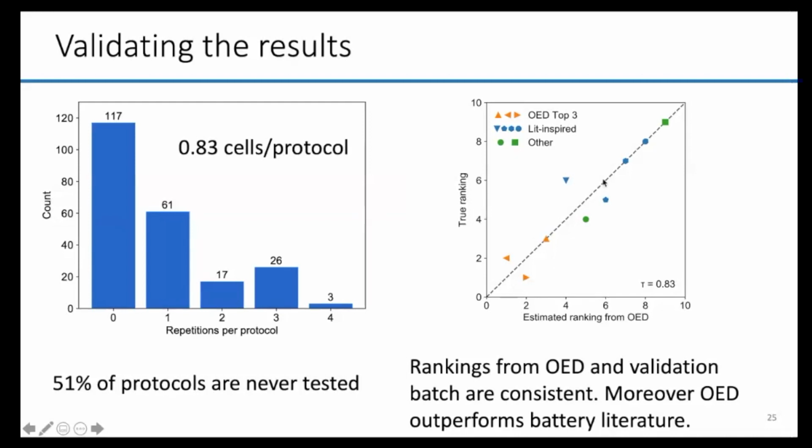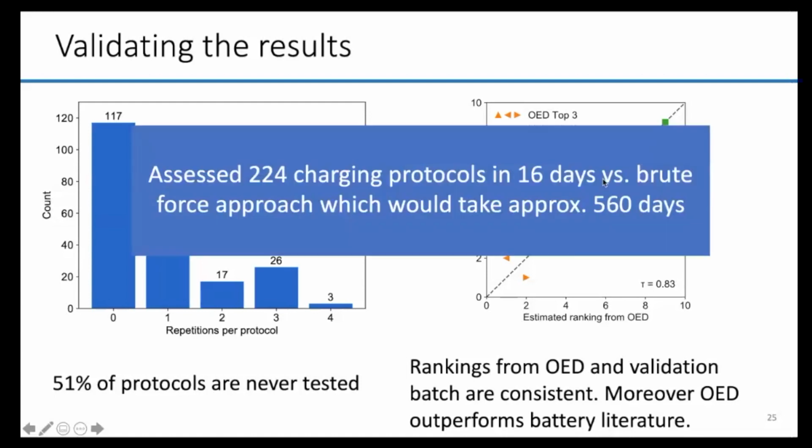So overall, this procedure was able to assess 224 charging protocols in only 16 days versus the brute force approach, which would have taken approximately 560 days. So this whole pipeline really enabled a great speed up in the analysis.